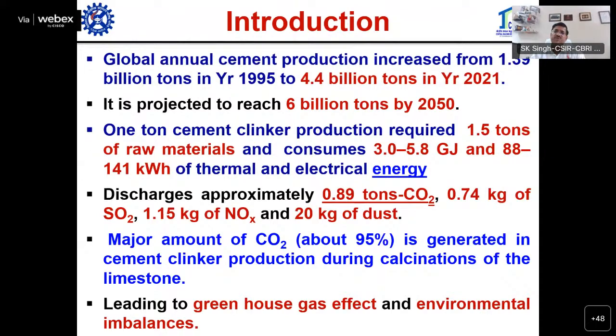So a lot of modification in the processing has been carried out by the cement industries, particularly in India, but still about 0.9 ton CO2 is produced through 1 ton of cement production, and 0.74 kg of SOx and 1.15 kg of NOx, and not less than 20 kg of dust. It's been a major challenge, a major issue with the cement industries particularly.